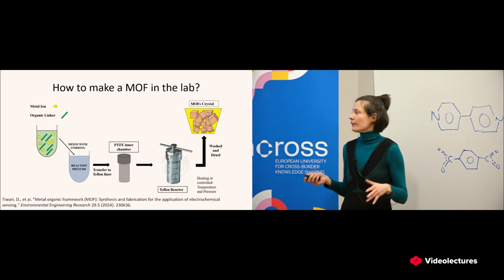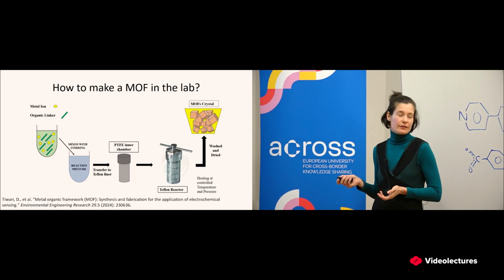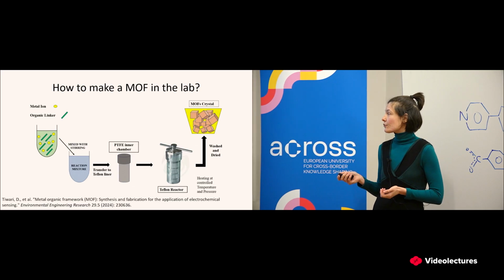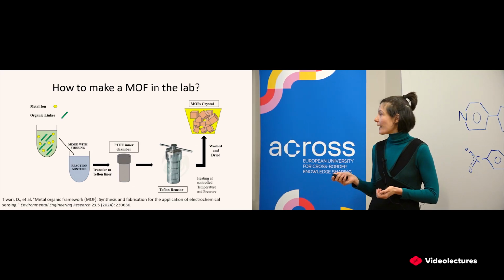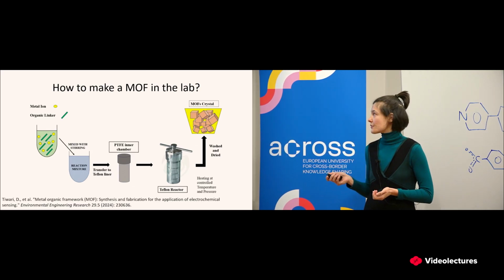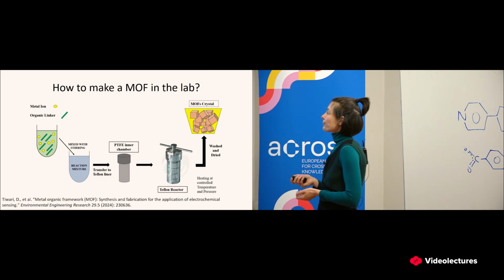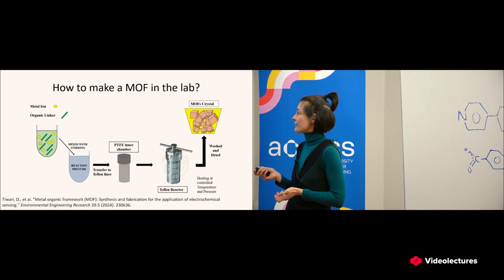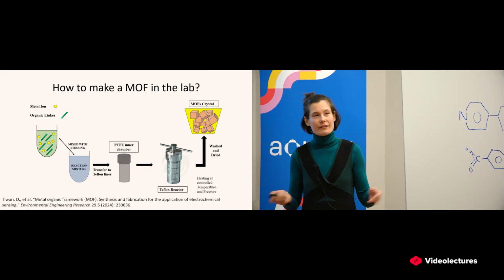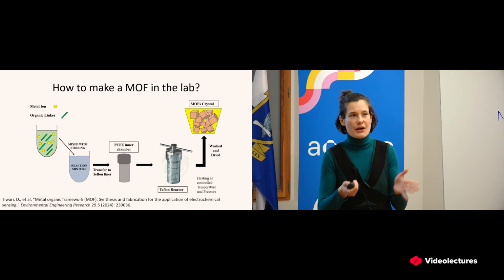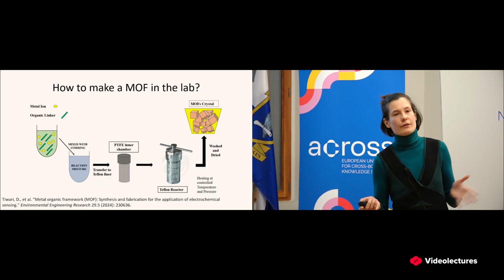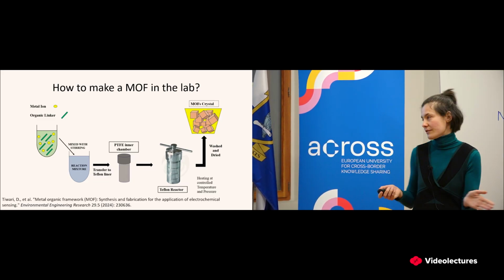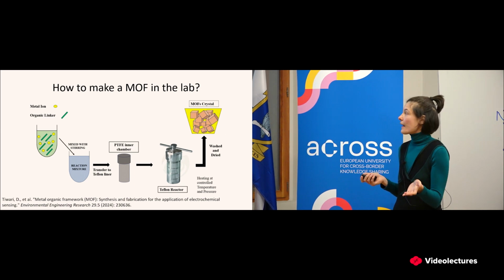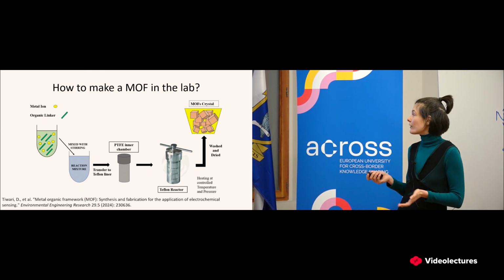Then traditionally MOFs are made in such a way that this reaction mixture is transferred into a Teflon liner, and this is then placed inside such a reactor, an autoclave reactor, which is then heated in an oven. And these reaction times vary, of course, but they are usually several hours or even several days. And then when you're done, when this time is over, you take this out.